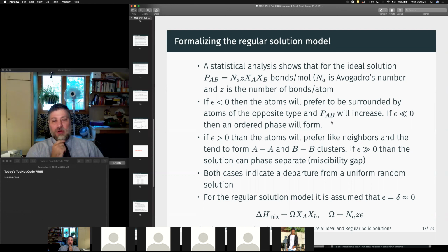We're going to form an ordered phase if it's a metal, or if it's small enough, we'll start to get ionic character to our bonding and we'll form a ceramic lattice. So if we have metal ions plus, say, oxides, with a large electronegativity difference, we form a completely ordered phase and form an ionic ceramic rather than a metal.